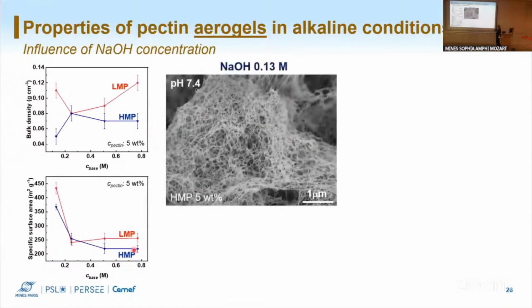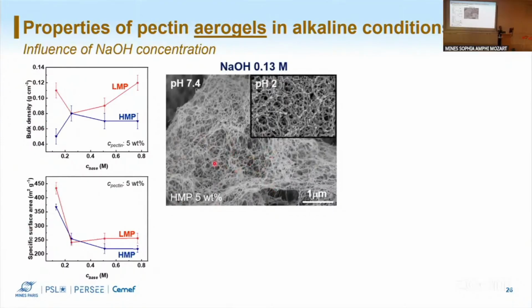We can see these properties depicted on the images of our structure from scanning electron microscopy. So here we are in the low concentration of base, so in the very beginning. We see we have small pores and a very fine structure, and here we see the structure at acidic conditions. So if you put one on top of the other, you'll see that they are very, very close.